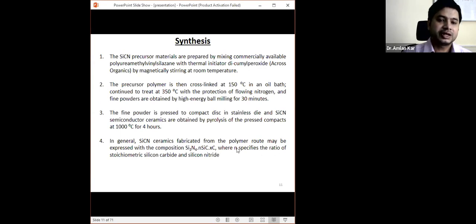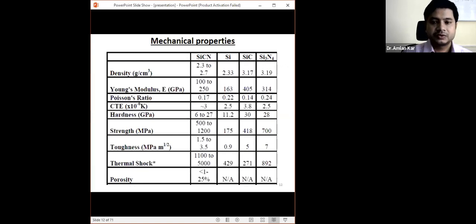You can see here where N is the specific ratio of the stoichiometric. So that depends on how you are preparing the ceramic particles. If you see the mechanical property, you can find out the mechanical property of the silicon carbonitride SiCN is more or less comparable to the other ceramic particles, but you can see the fracture toughness or the toughness of the material is substantially low compared to SiC, Si3N4. These are the most commonly used ceramic particles. And one of the important factors, you can see the thermal property is very high and porosity is very low.